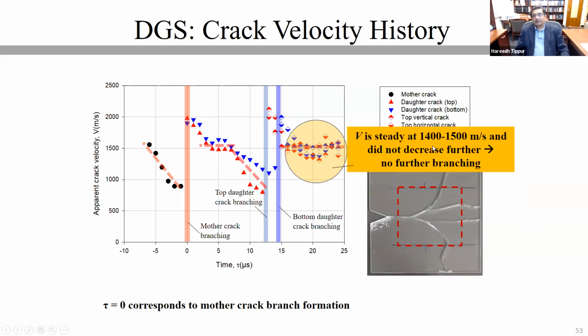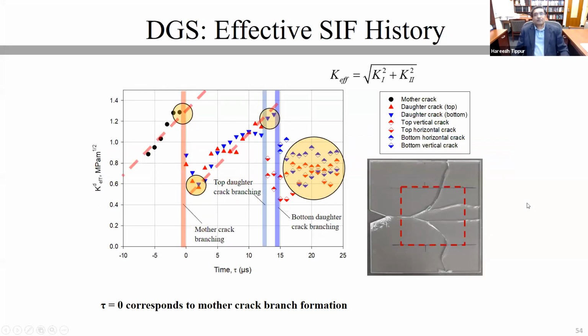So in the last part over here, the velocity never decreased from 1500 meters per second. And obviously, consistently, we did not see any branching as we had seen before. We also have extracted stress intensity factors without any details here. The effective stress intensity factor, the vectorial sum of your K1 and K2, here reached a value of somewhere around 1.2 to 1.3 megapascal root meter, which is similar to the previous smaller specimen, where I had a value here somewhere around 1.1 to 1.15.